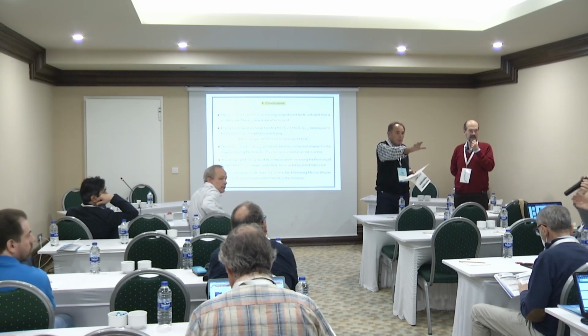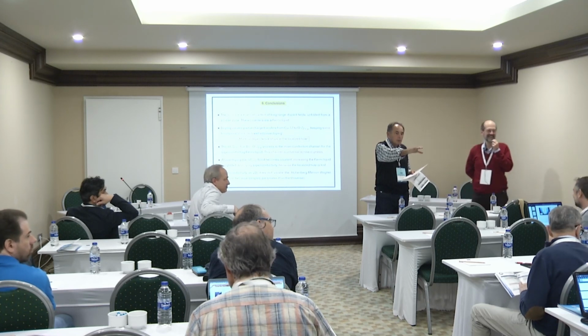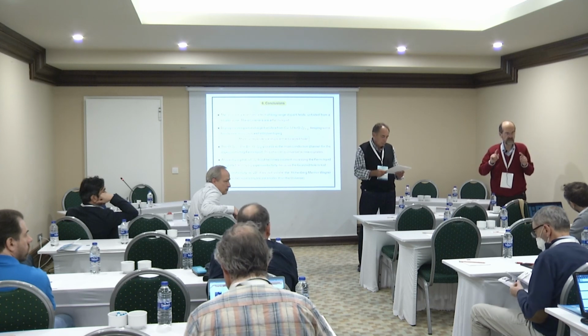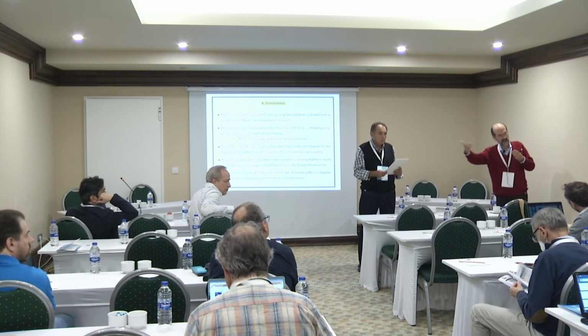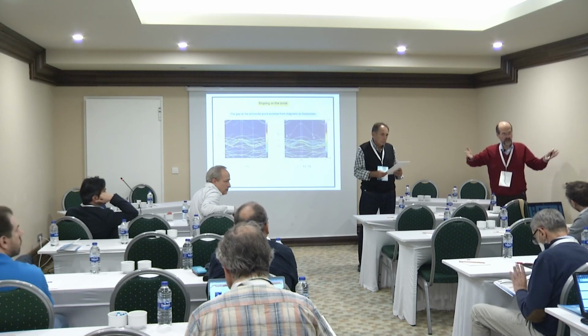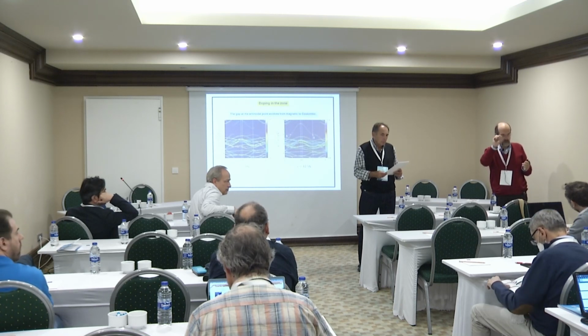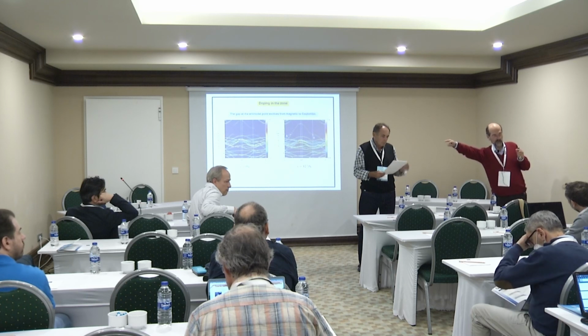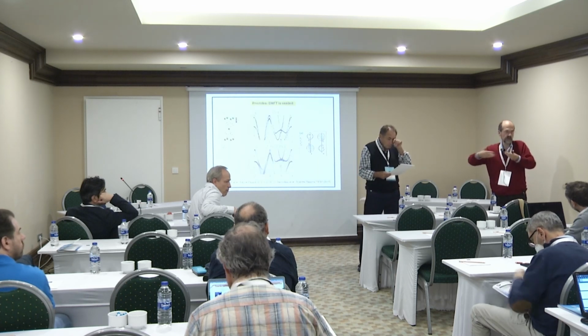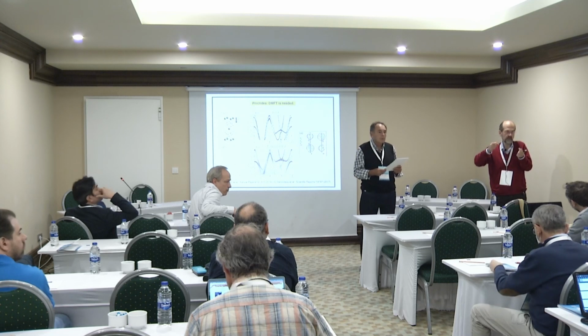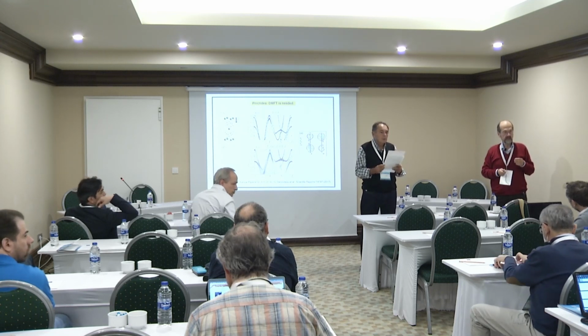Quick one, please. Just concerning this supercell calculation. The bands can't just simply stop, so is this arc bending backwards again, or is it a pocket? No. You have a small zone, and in this small zone you have several Fermi surfaces which all properly close upon themselves. Then you unfold this small zone into a large zone, and each point which crosses the Fermi energy maps onto some point over there. But of course, like a superposition. It's not a one-to-one point. But the band from the arc goes then back again into the arc.